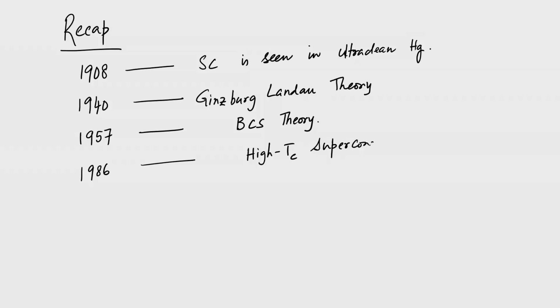So, these classes of superconductors have been seen, which have TCs ranging from 40 Kelvin to about 200 Kelvin or even larger than that, and these are all copper oxide based superconductors. And then in the early 2000s there was the discovery of iron based superconductors and so on. So, various developments took place regarding the understanding of superconductivity, many of them empirical. Let us see some of the results that were proposed and were found to be true, at least in certain superconductors. So, some of these empirical rules.